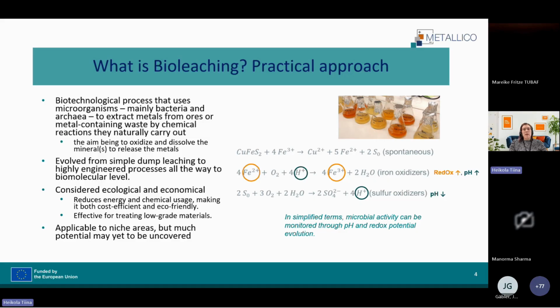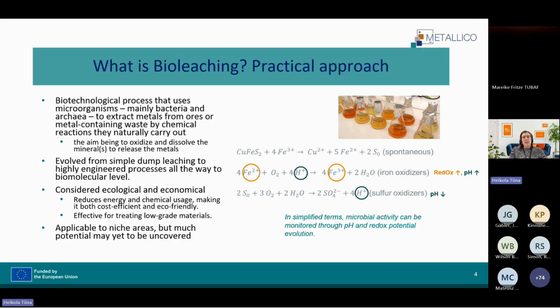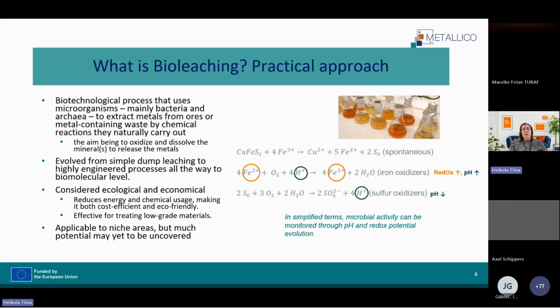And in the practical way, in simplified terms, the activity of the microbes and as a result of that, the leaching success can be monitored through pH and redox potential evolution. And as Päivi already mentioned, originally the bioleaching is evolved from a simple dump leaching, but nowadays it can be even a biomolecular level engineered process. And it is usually considered ecological and economical alternative to conventional techniques. The advantages are reduced energy and chemical consumption, which are particularly an advantage when treating low-grade materials.